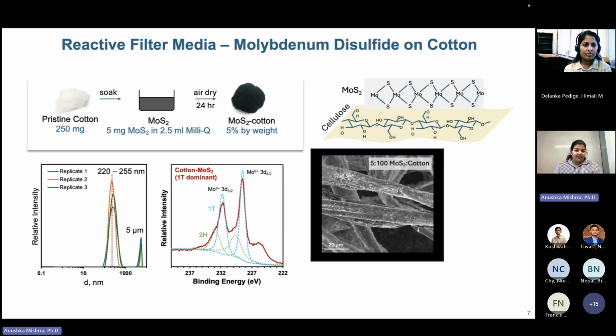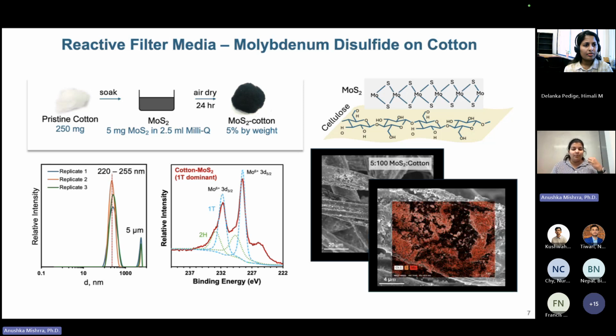Then we put the material under the microscope. So what here you're looking at are cotton threads, which are at least 10 micrometer in diameter. And the bright particles, like the bright regions on it, is definitely the particles. And so the way to know that these particles are MOS2, we did EDS, which is looking at the elemental maps on the cotton fibers. And what we see is that most of the surface is coated with molybdenum and sulfur.